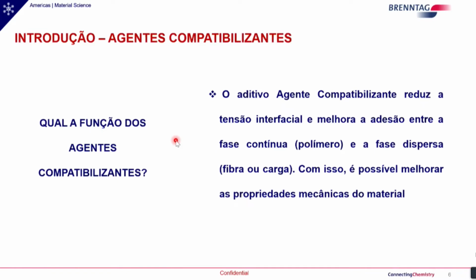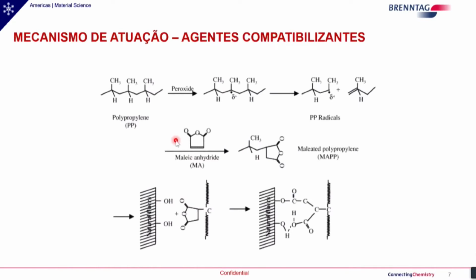That has an impact in the production of the polymer. The impact is that there is no interaction between these two different phases. These materials don't connect with each other. So a way of being successful in using these agents, which are foreign to polypropylene, is precisely the use of a compatibilizing agent, which then becomes a bridge, so that these two different phases, polar and apolar, can have a connection.